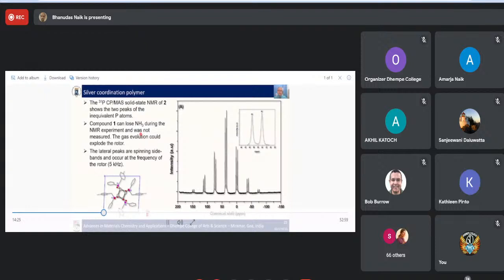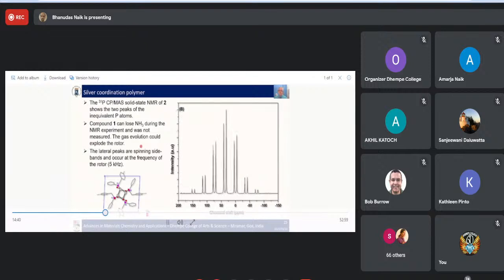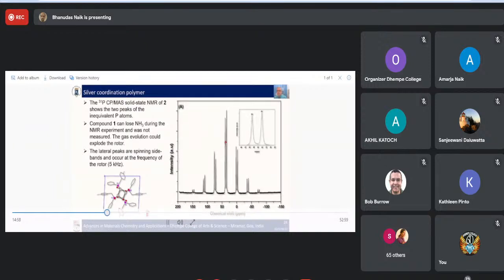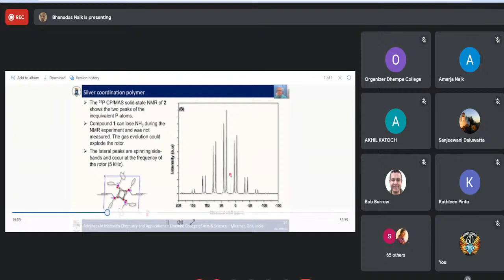In fact, we tried doing this, but even just closing the rotor, the cap popped off right away, even before we put it in the machine, which is really quite good, because if it remains closed, it can explode the rotor, and of course, that'll destroy the probe. And also, Burrow managed to use Quantum Espresso to simulate the solid state NMR, and you can see the simulated spectrum is really quite similar to the experimental. This is experimental, and this is simulated.